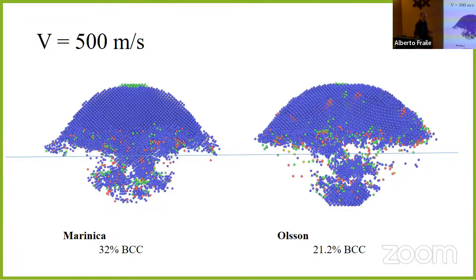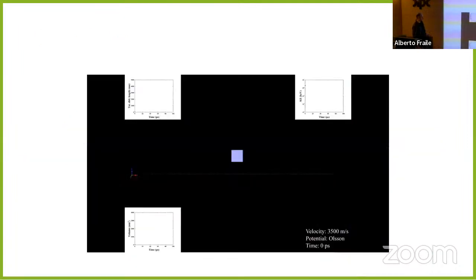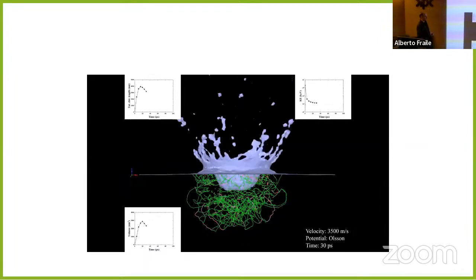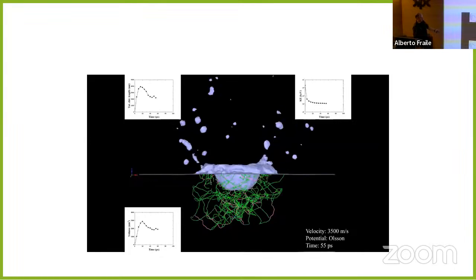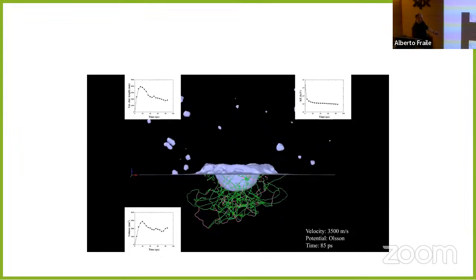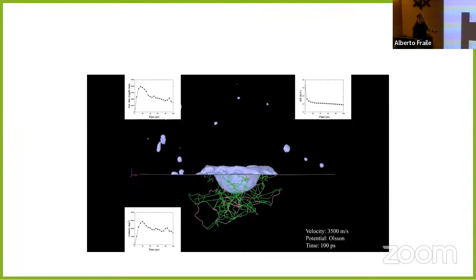Yes, thanks. So yeah, the two potentials here are showing some differences in the amount of recrystallization, even in the low velocity regime. Then this is a simulation of what we see when we have high velocity impact. Okay, so you see that the tungsten is like water. This is just 3.5 kilometers per second. And so we have this crater, we have the rim, we have a lot of atoms scattered, like individual atoms and also clusters, and we have all these dislocations in the target.